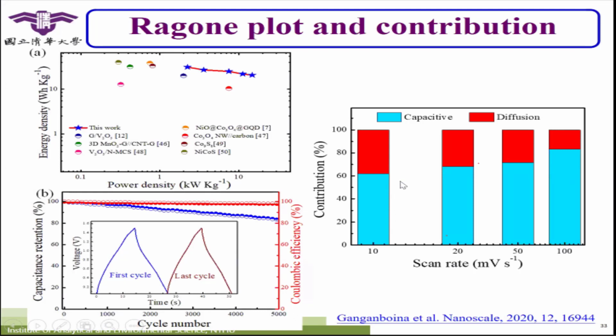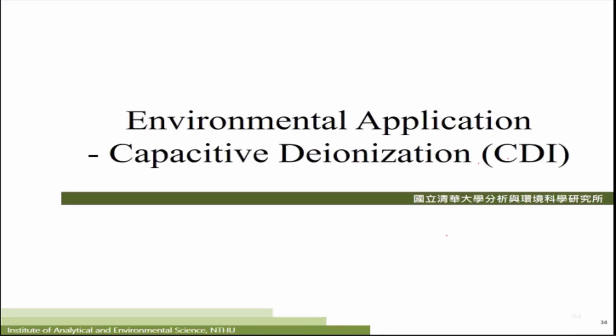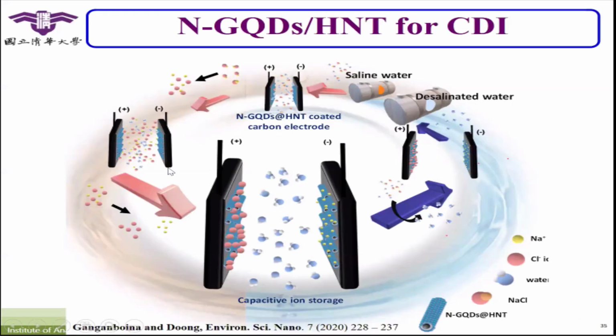Here we analyze the contribution of the diffusion and capacitive. We always will see that when you use a high scan rate, the capacitive contribution will be much higher. It means that the GQD actually plays a very important role here. So not just for energy application, you also can use these materials for capacitive deionization for environmental application. The same idea is the same.